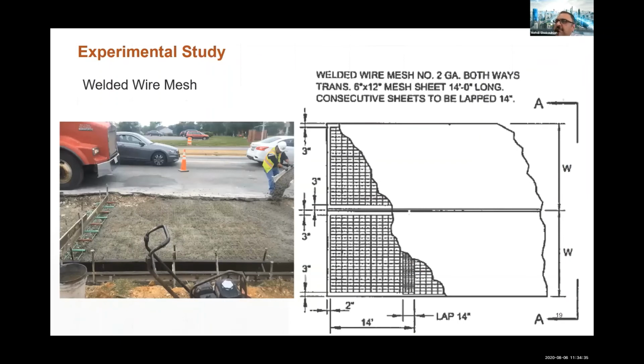So in terms of the reinforcement, this is what is basically provided in a drawing, but we observed that in most of the cases, the reinforcement that was even indicated in the drawings was not seen in actual construction. So sometimes the spacing between the rebar, the wires, was different from what was indicated.